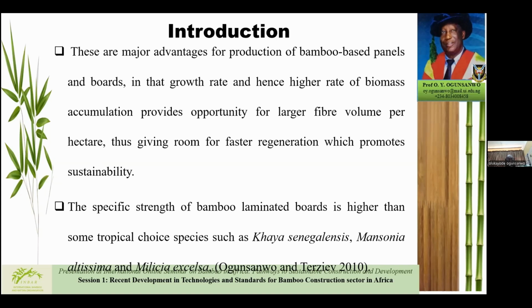One of the key issues here is found in the strength properties of bamboo. We discovered from the specific trends in some of the researches that were carried out in the past that the specific strength of bamboo, which gives the relationship between weight and density, is higher than some tropical choice species like Khaya senegalensis, Mansonia altissima, Milicia excelsa. These species are sought after. And in fact, some of the reasons why we have a high rate of deforestation is because people go into the forest to look for these species. And this was discovered in our research, Ogunsanwo and Terziev in 2010.